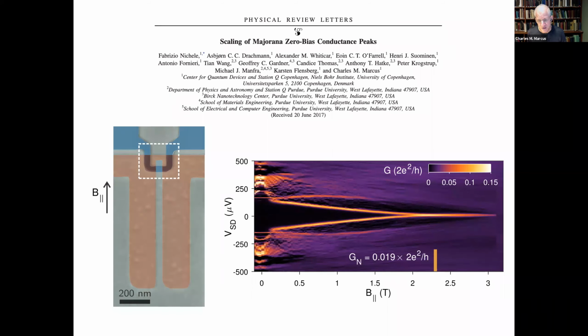So the two-dimensional versions of the superconductor-semiconductor systems are also yielding these characteristic zero energy states at high magnetic fields. But I want to point out that going up to 1.5 to 2.5 Tesla, these are not magnetic fields that superconductors like very much. And moreover, these are magnetic fields that have to be oriented rather precisely along the axis of the wire. And nobody likes putting 2 Tesla on a superconductor, let alone having to put 2 Tesla on a superconductor with less than a degree of fluctuations in how it's angled.